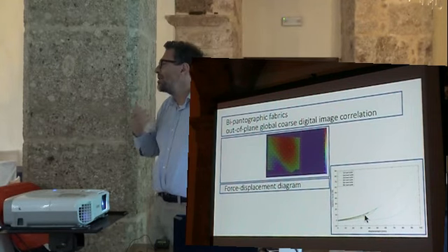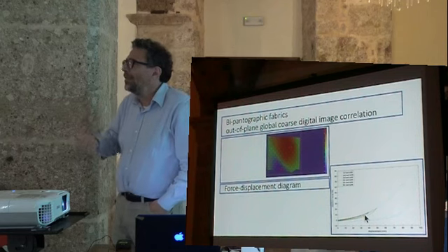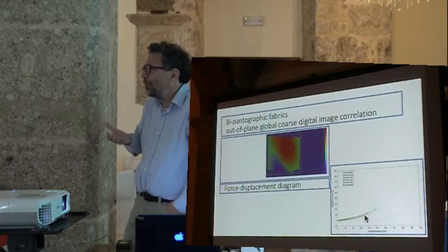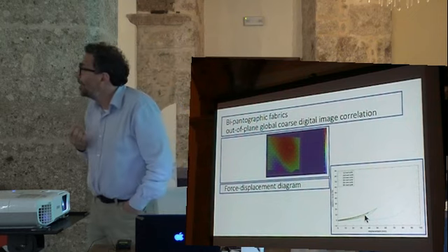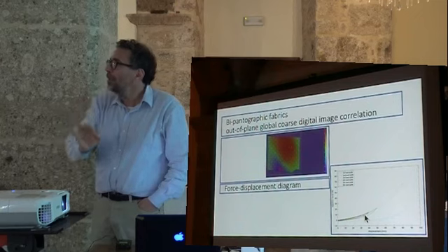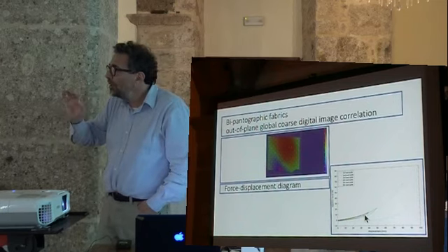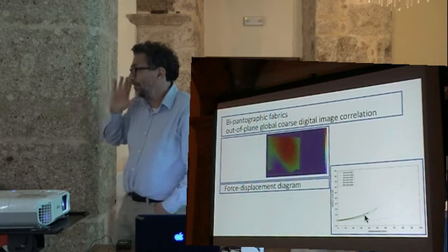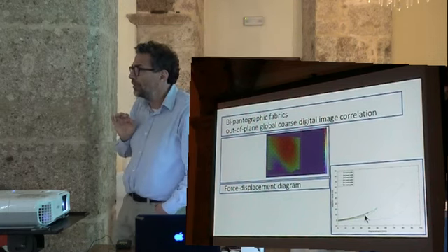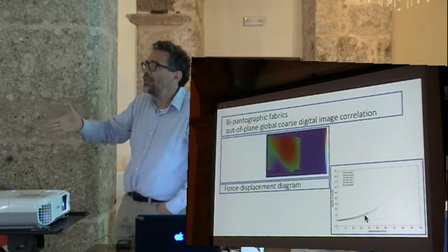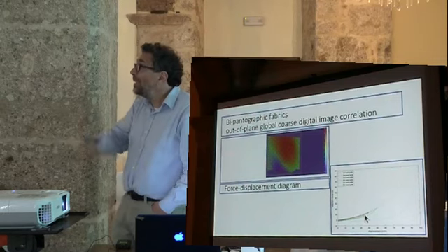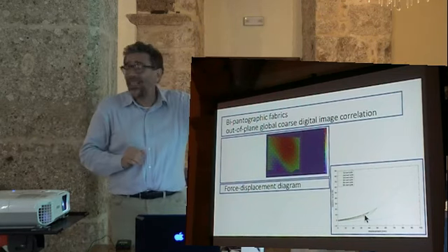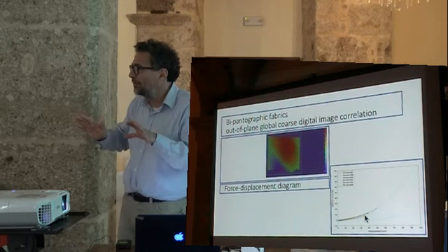I think let us give credits. We say that you must give to Caesar what is owed to Caesar. I don't know how to say it in English. It is a biblical statement. This idea for doing perfect pivots is due to a student, somebody with a master's degree, Maciej Golasewski, if I pronounce it right, from Warsaw University of Technology. He dared to print this specimen in this way. And when they told him, but there are some grains, he said, okay, I will do run-in and I will get rid of these grains. So this is the main trick which allows us to have large displacements.